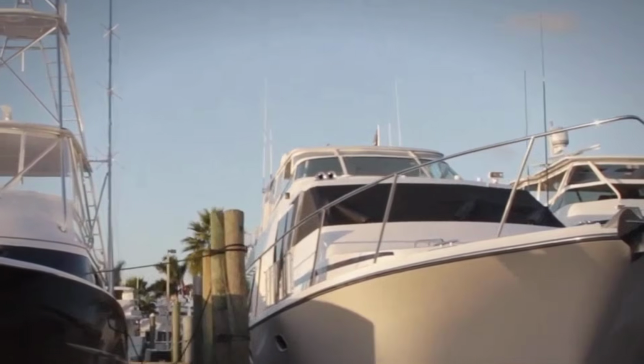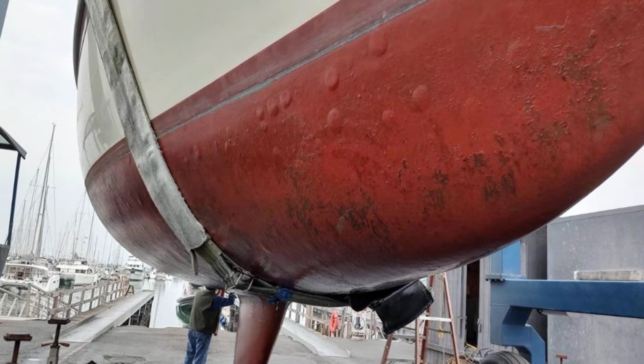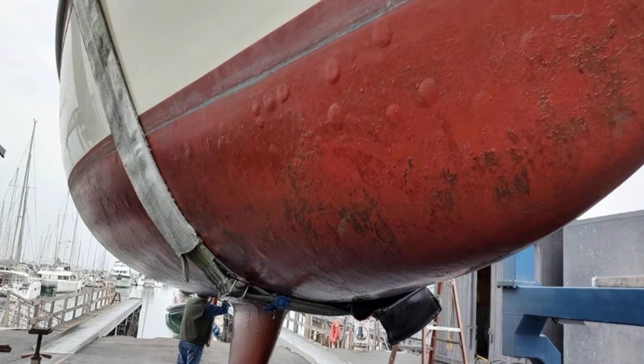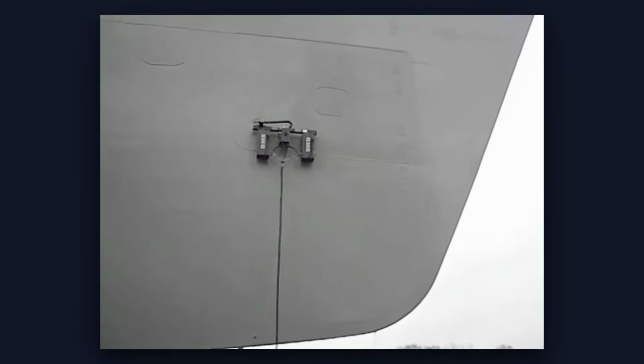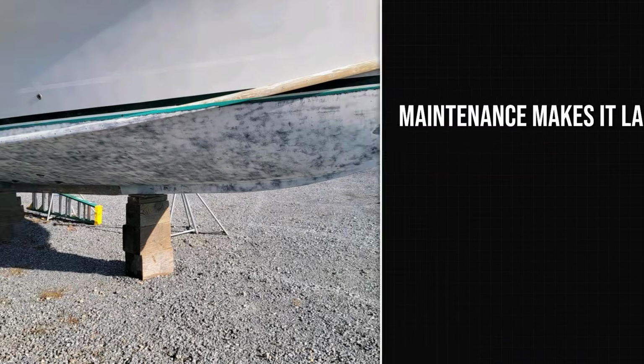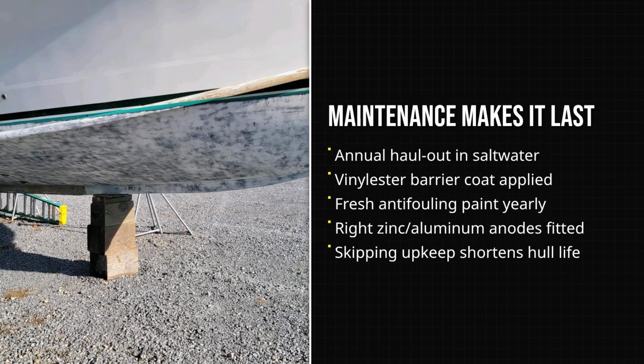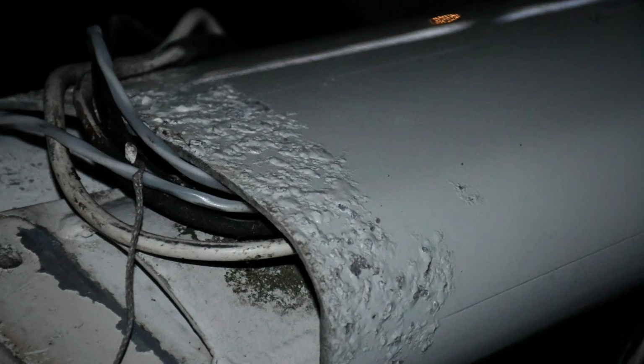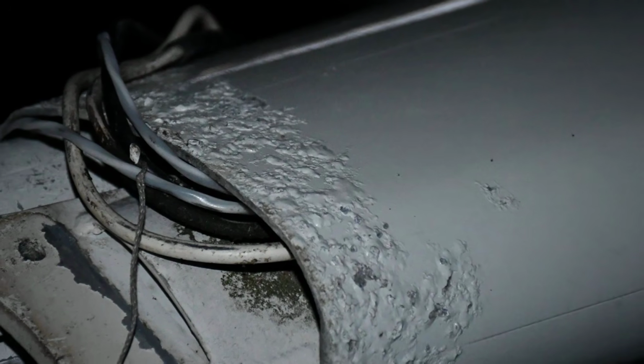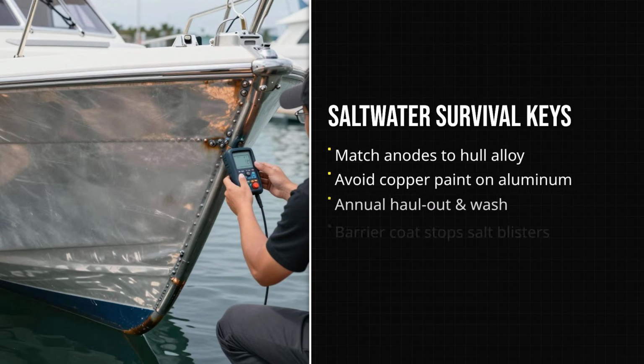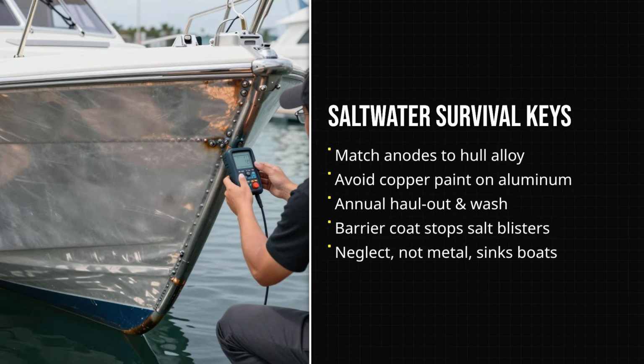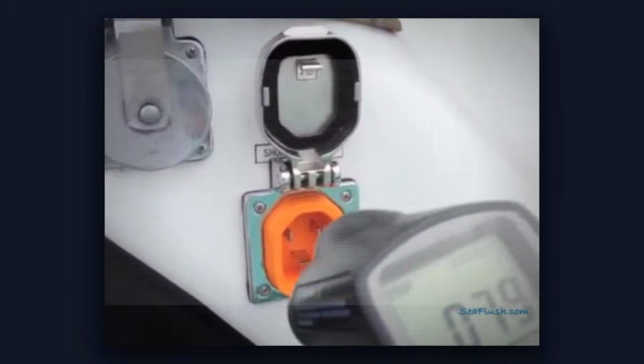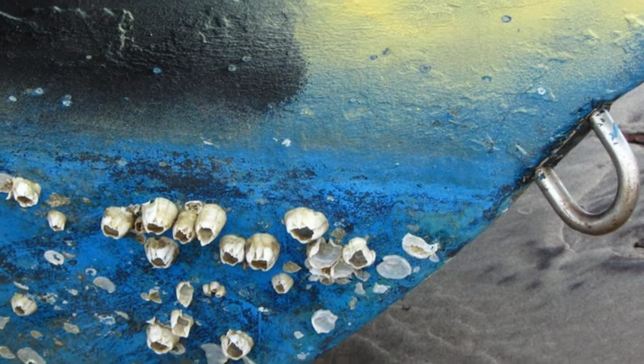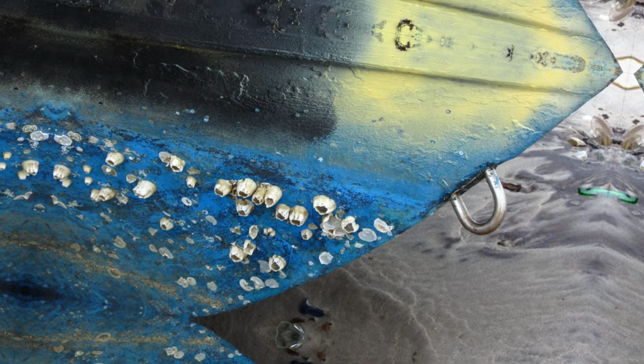In saltwater, particularly in warm water where osmotic chemistry in fiberglass is more aggressive, and where galvanic corrosion in aluminum is accelerated, the outcome depends entirely on maintenance discipline. A fiberglass hull built with vinylester resin, hauled annually, and protected with a proper barrier coat and anti-fouling bottom paint will outperform a neglected aluminum hull every time. A well-maintained aluminum hull with correctly specified anodes, no copper anti-fouling, and a galvanic isolator on shore power will outperform a neglected fiberglass hull. Neither material survives deferred maintenance in saltwater.